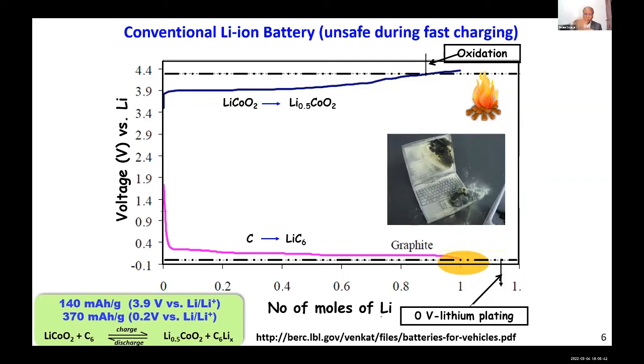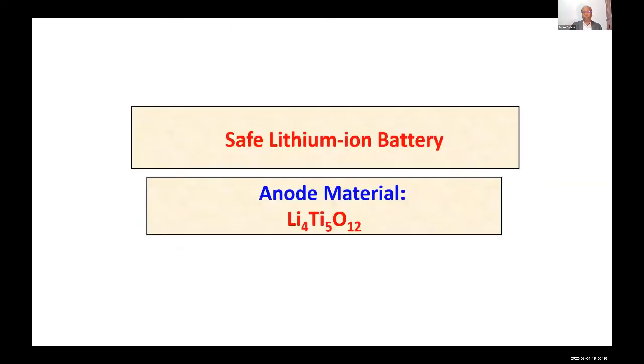And that dendrite growth, a sharp needle, can pass through the separator, which is about 10 micron, and it can touch the positive electrode, thereby leading to so-called internal micro-shorting. So you should always avoid fast charging anytime you use graphite cells. The typical charging rate is about 2 hours, but discharging you can do fast. Because in the discharging, you are extracting the lithium from lithiated graphite and then inserting into the so-called lithium cobalt oxide. That can be at any rate. But insertion or the charging should always be done at a slow rate, typically about 2 hours.